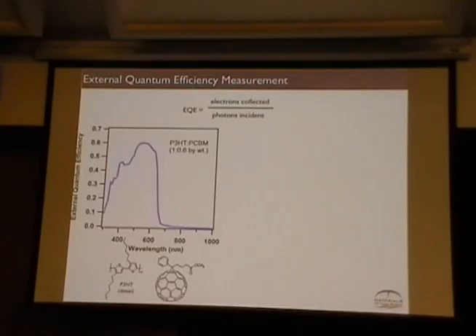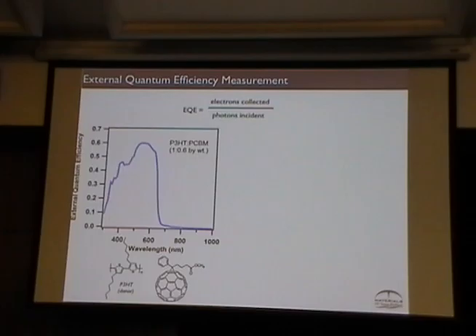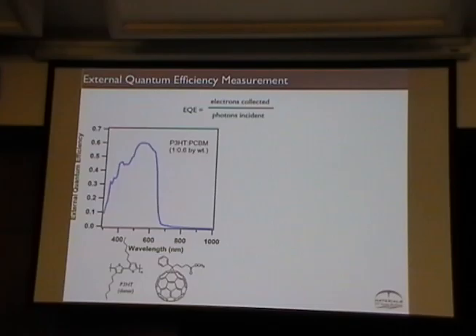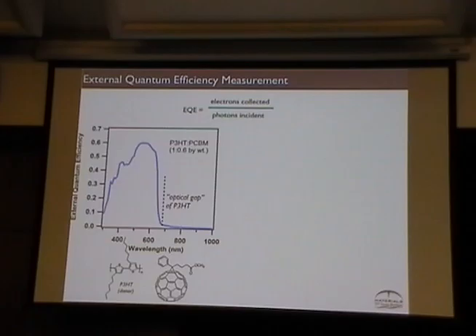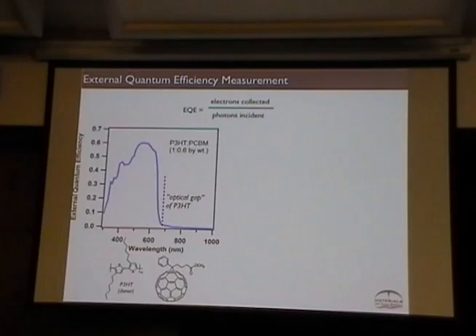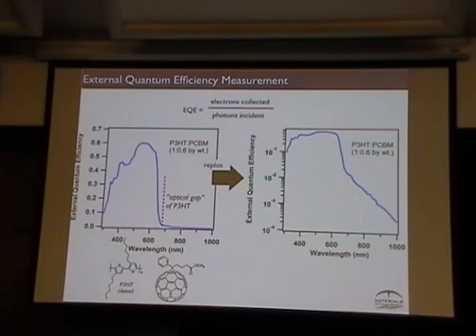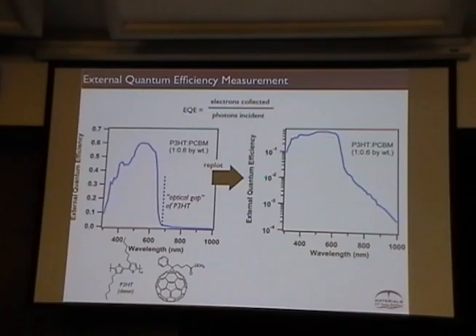That's a specialized technique that many of us don't have. What technique do a lot of us have? If you look at the external quantum efficiency of a material — people typically plot on a linear scale versus wavelength — here's P3HT/PCBM, and for an okay cell the EQE is 0.6, meaning every photon I illuminate I get 0.6 carriers out. The optical gap of P3HT/PCBM is here. If you just take that data and plot it on a log scale, you suddenly see a bunch of features beyond the absorption edge — suddenly you're generating charge, not very efficiently, but there are a lot of states out here that if you put energy in, you get charge out.